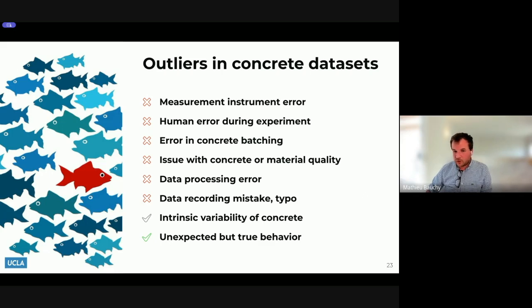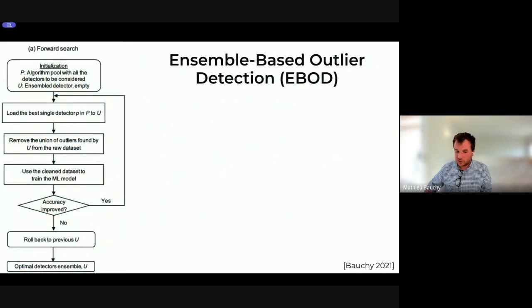So we spend quite a bit of effort on developing some tools to identify outliers. And so that's one approach that we have been using here. I won't go into too much detail, but basically the main idea is that there are many different algorithms to detect outliers, and each of them might be good individually. But the approach that we have been using is to rely on an ensemble of outlier detection algorithms. And the idea of this approach is that we build a pool of outlier detection algorithms. So this can be density based, by looking at the density of data points. It can be distance based, can be angle based, etc.